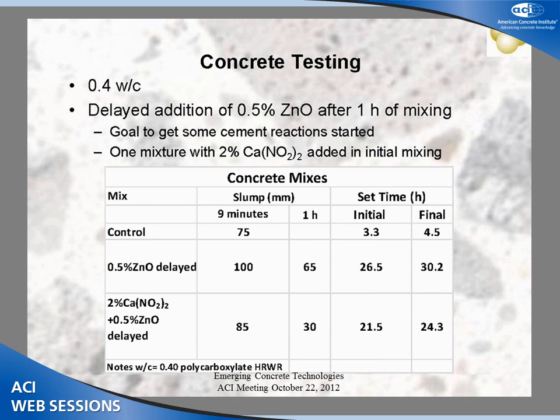The control mix was produced at about a 3-inch slump, 75 millimeters, measured after 9 minutes. After 1 hour, the slump was not measurable. It had lost all of its workability and plasticity. In the case of the mix made with a 0.5% zinc oxide, again as a delayed addition, the slump was about 4 inches after 9 minutes, and then after an hour, it was between a 2 to 3 inch slump, 65 millimeters.